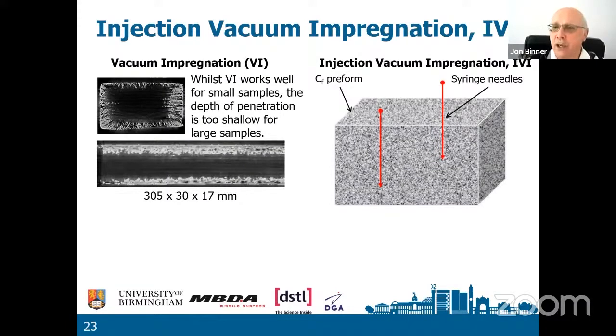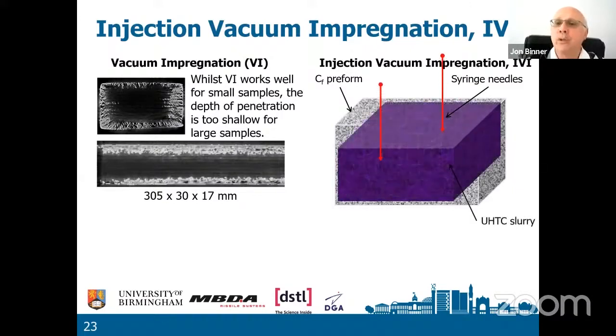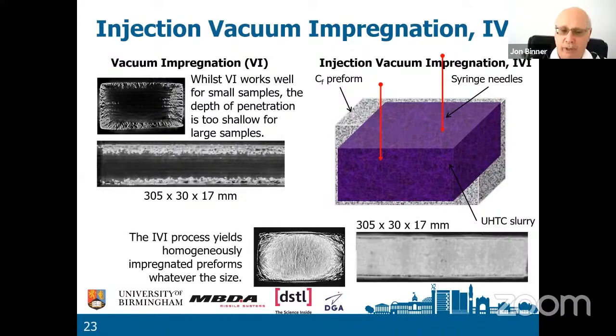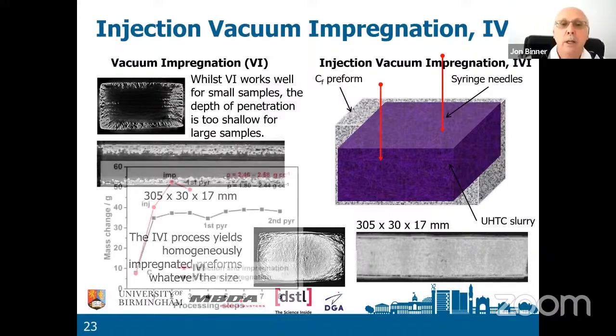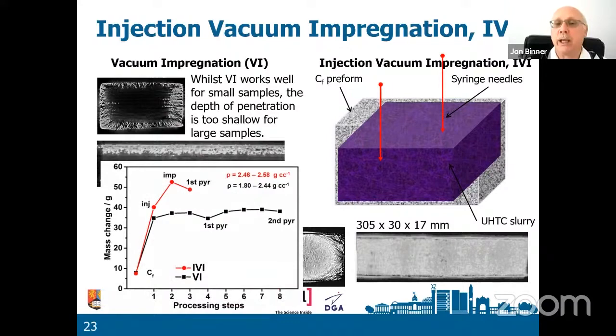We developed the injection vacuum impregnation, which we know as IVI. So you take a syringe full of your slurry, you plunge the syringe into your preform, and then as you withdraw the syringe, you squeeze the slurry into your preform. So now you're able to fill the preform from the inside with your slurry. And it works absolutely beautifully. And you can get very, very homogeneously impregnated preforms, and it doesn't matter what the size is. So you can have a look at these things, and we shall see shortly, and you can make really large plates.